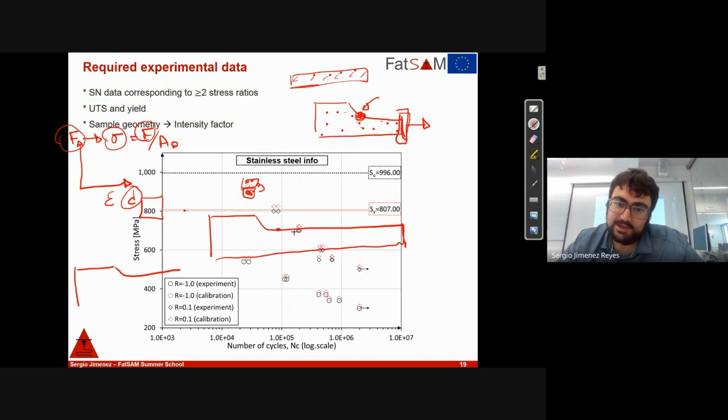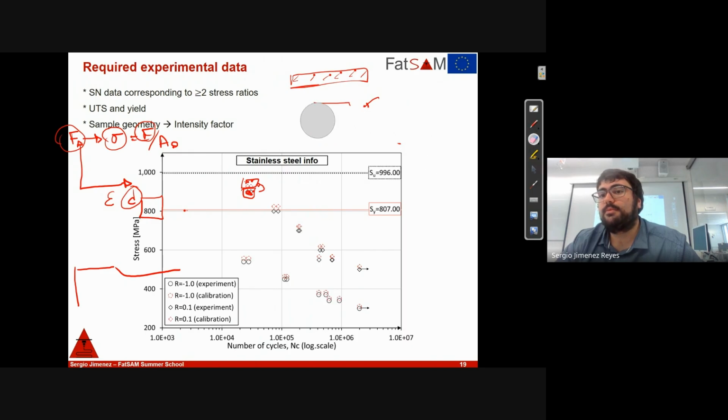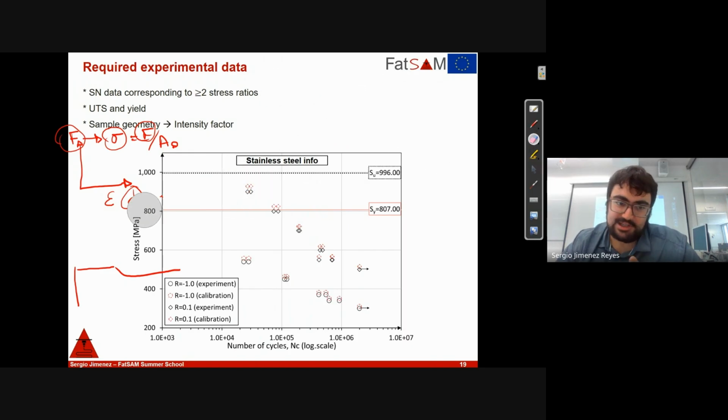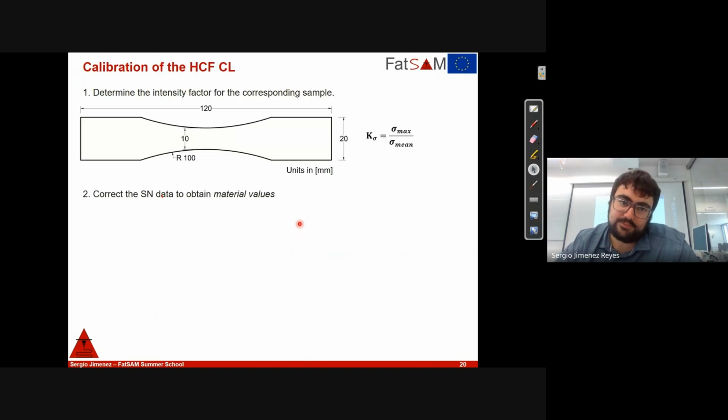If you run the tensile test in your model, you will see that the non-linearities, even though they start here, rapidly propagate towards the center. And the stress distribution is pretty much uniform during all the inelastic process. The problem with fatigue is that you are never entering the inelastic process in a visible manner. You are always in the elastic regime, so the stress distribution here is not homogeneous. This kind of test doesn't work, for example, for big deformation with non-homogeneous fields. Yeah, but in this case, you will stay in small strains under the elastic domain. So that's why you need to do this shift.